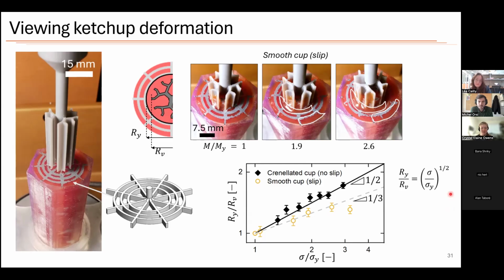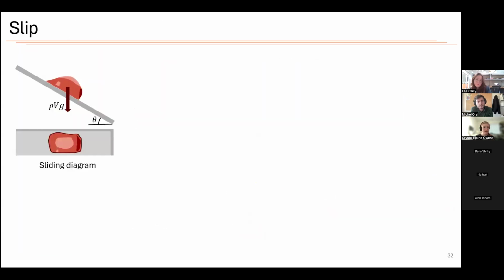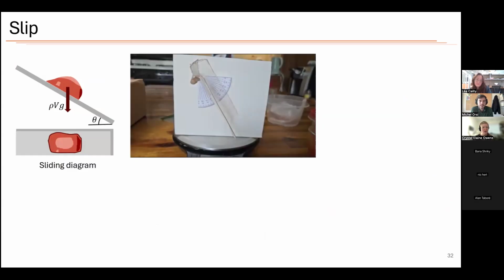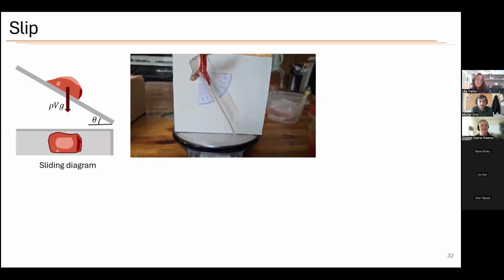But in this case, slip is dependent on the interaction of the ketchup with the surface that it's on. So rather than using this 3D printed material, we set up another test to measure slip on the ketchup bottle itself. For this test, the idea is you have ketchup sliding down an inclined plane under the force of gravity. With the other half of the ketchup bottle, I mounted it on an angled holder.